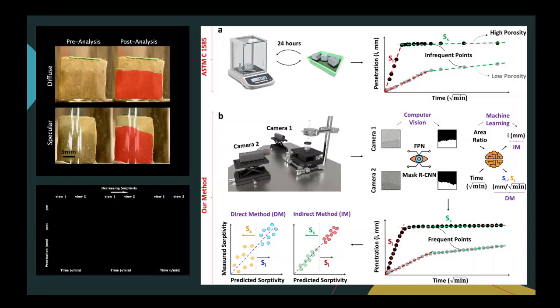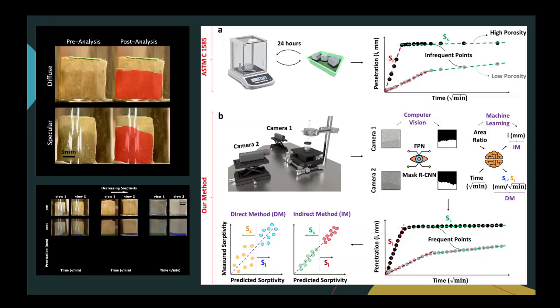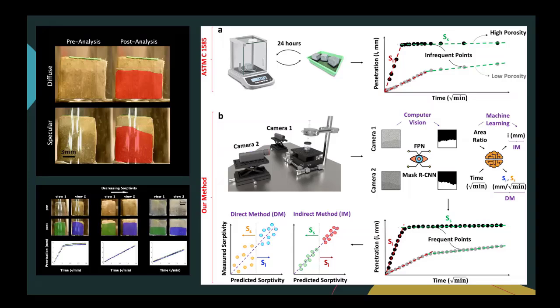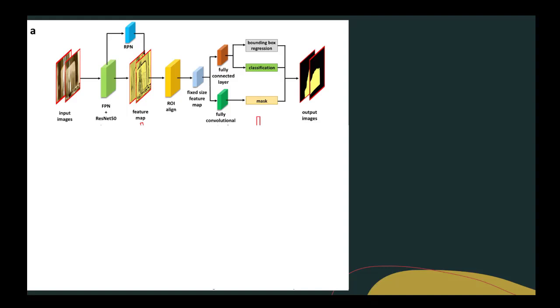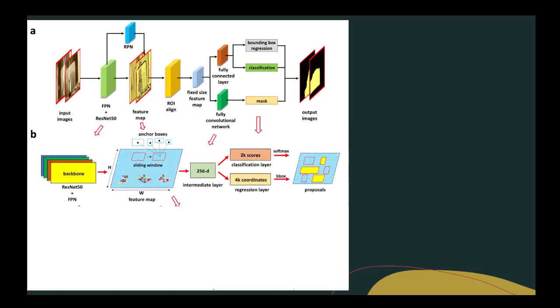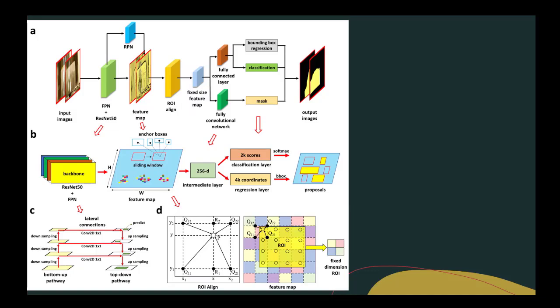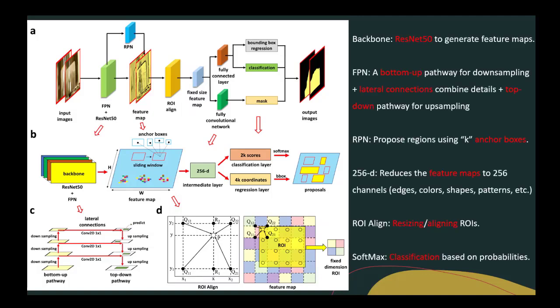And then this video shows how by just looking at the image, we can combine the area and time value using deep learning to predict penetration as a function of the square root of time in real time. So the computer vision code, we wrote it from scratch, and it has input images, which are RGB images. It has segmented binary output. And in the middle, it has feature pyramid network, ResNet 50, regional proposal network. Also, we realized that if we remove ResNet 50 and RPN, and we solely rely on FPN, like we have bottom up and then top down, downsampling and upsampling, we can quickly predict the water level.